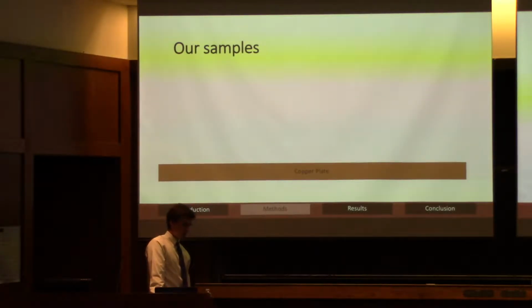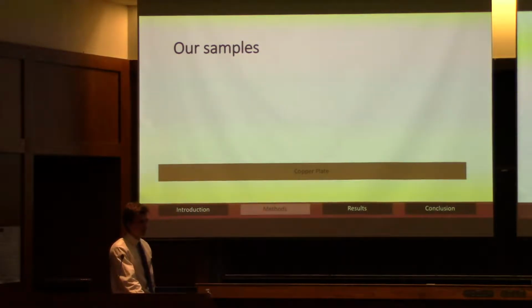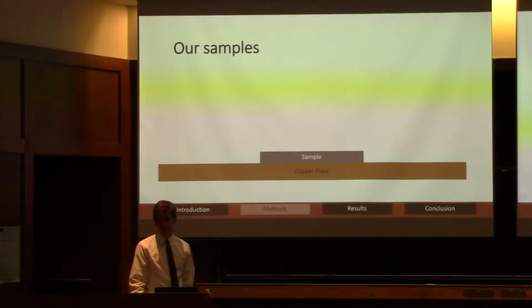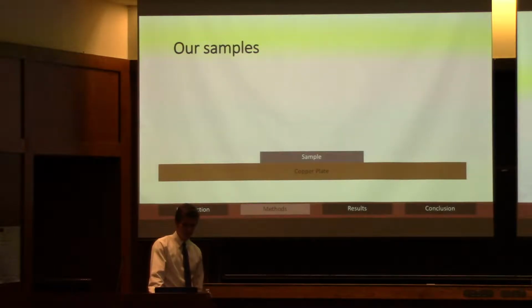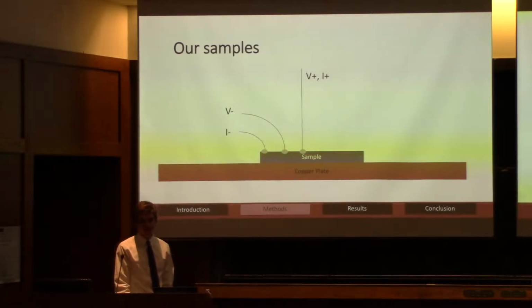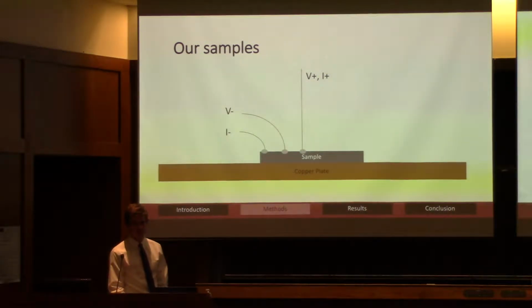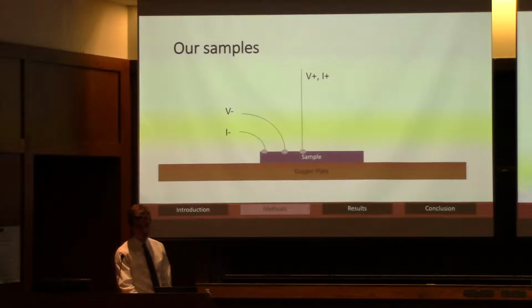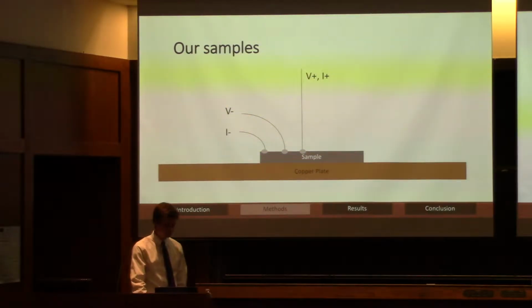So to give you a breakdown of what those samples actually look like, we start with a copper plate, and we put our sample on top of that. I am working specifically with iron telluride selenide, and that goes on top of the plate, and then we add our wires on top, attach those with silver paint, and then apply voltage and current across this. Now this sample goes inside our magnet chamber that's vacuumed out, that we can cool down from room temperature down to 5 Kelvin, and then we can change the strength of the magnetic field and the orientation of the sample with respect to that magnetic field.